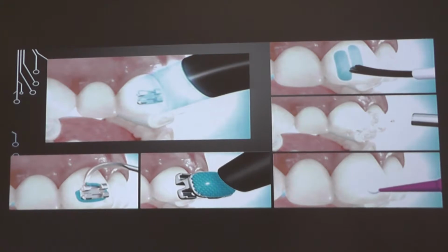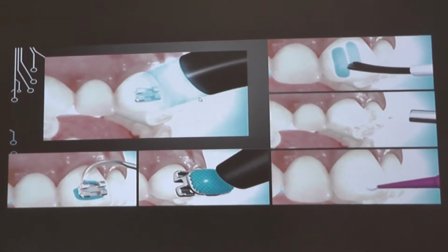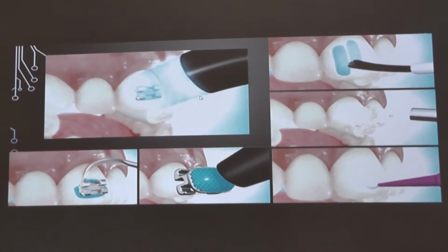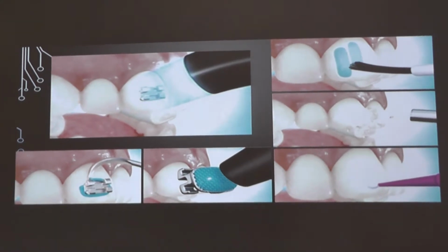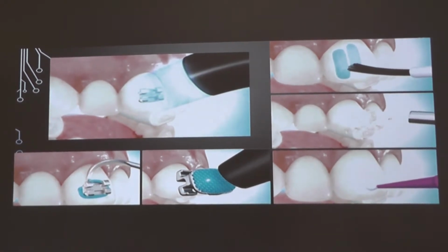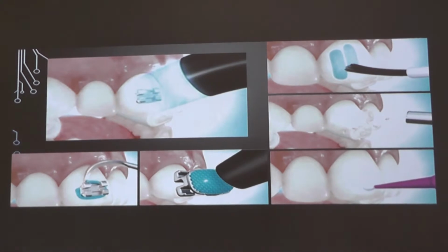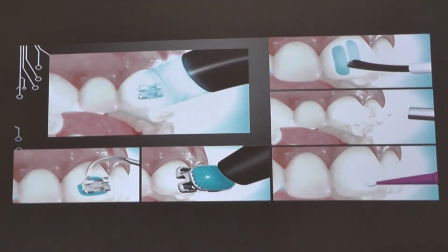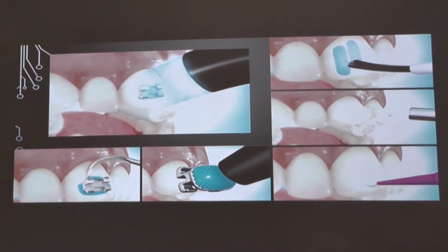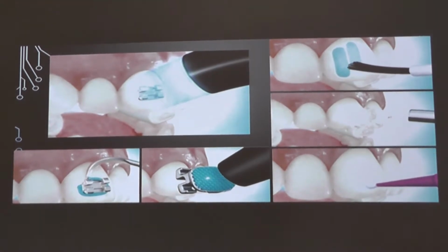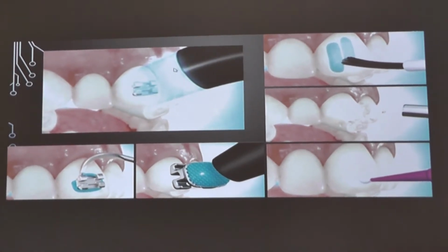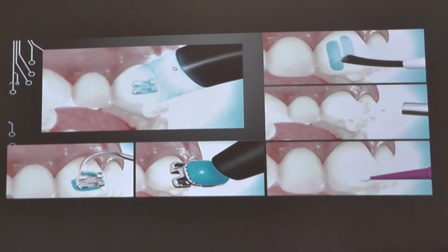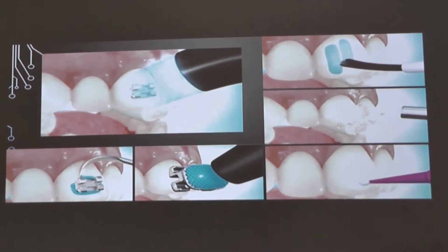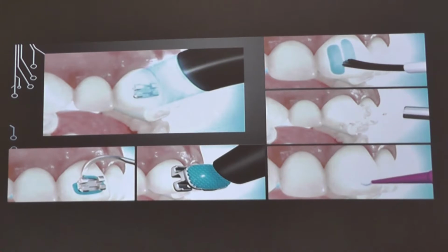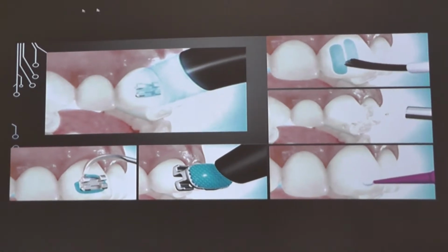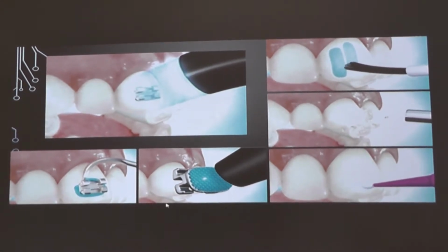So it is always, this is not a good angle. It should always be at an angle of 30-45 degrees from two sides. So if you cure for 10 seconds in total, do it 5 seconds from one side and 5 seconds from the other. It can be mesial distal or gingival incisal. However, when cured in such a manner, they do show a degree of conversion that is similar to chemically cured adhesives. And they are easier to work with.